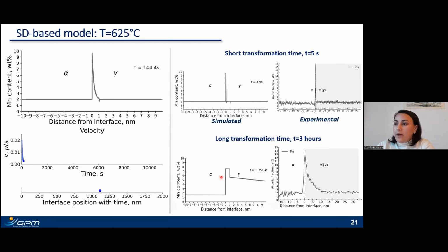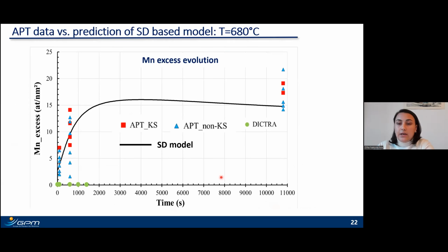And if we compare quantitatively the amount of manganese segregation measured experimentally with the result obtained using the solute drag-based model, we can see that it provides a more convincing comparison than the result obtained from Dichter. I just would like to mention that on this slide, I show you the comparison in the case of 680 degrees Celsius transformation temperature instead of 625. At this temperature, we had more data, so we can provide better statistics for comparison. But I assure you that we observe a similar tendency also in the case of 625.